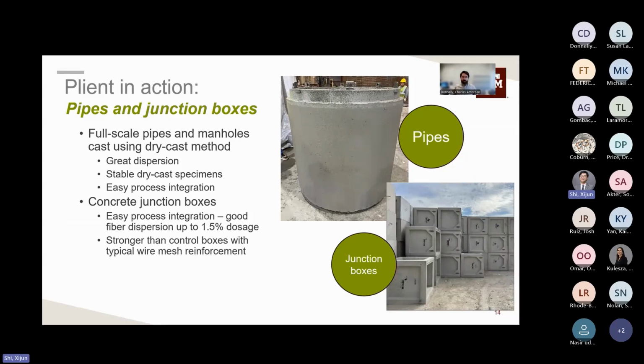So on the top here, you see full-scale pipes and manholes cast using a dry cast method. And these have the Plient fibers integrated throughout. What was observed was great dispersion of the fibers and stable cast conditions. And it was very seamless to integrate the fibers into it. I have a cool video coming up that I'll show you. Additionally, concrete junction boxes were constructed with up to 1.5% by volume Plient fibers. And it was observed that we were able to achieve easy fiber integration and improve the control box strength compared to the typical wire mesh reinforcement.